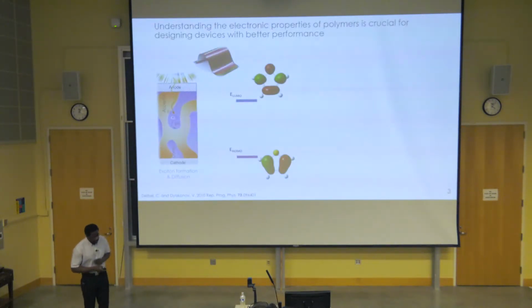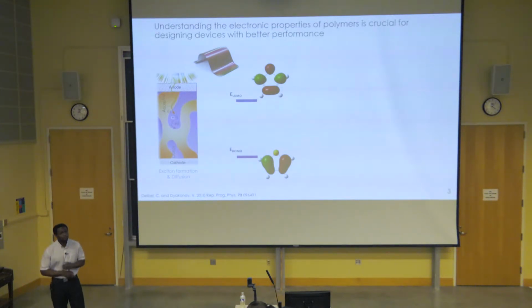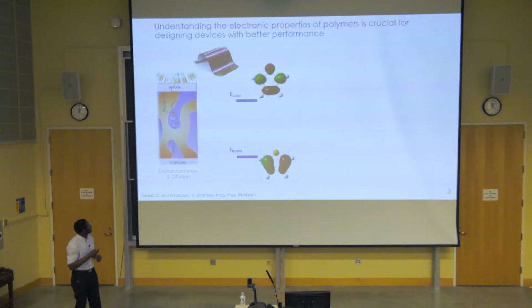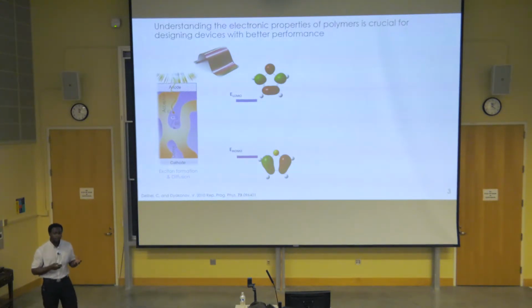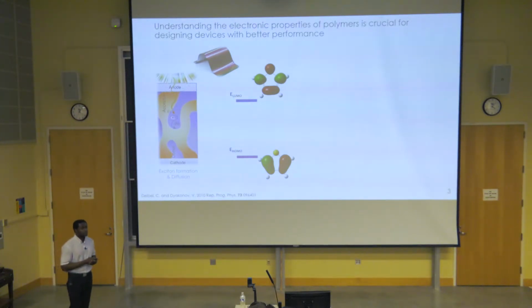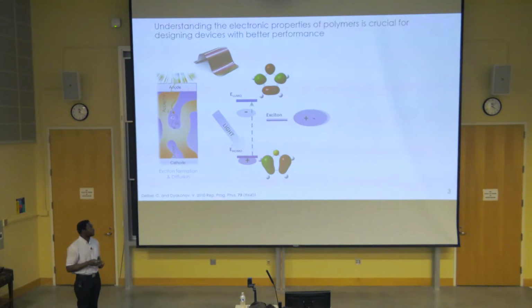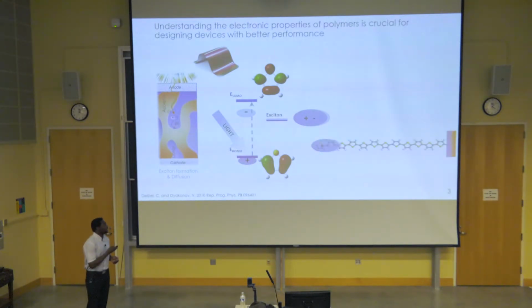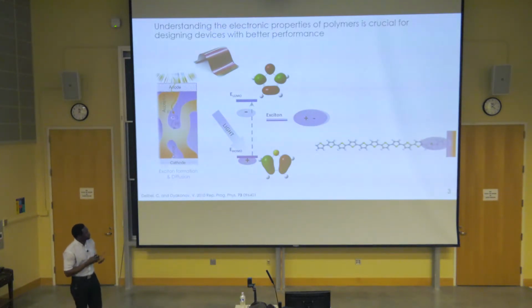And if you take a closer look at photovoltaic devices, one of the best performing devices currently is the bulk heterojunction solar cell, where the active layer of the device is made of a mixture of a donor and an acceptor, where the donor material is a polymer, and the acceptor can be a polymer or usually another small molecule. Within the donor material, light is absorbed and an electron is excited from the highest occupied molecular orbital, leaving a hole behind, to which it then combines through Coulomb attraction to form an exciton. And once this exciton forms, it then diffuses to the interface between the donor and the acceptor material.